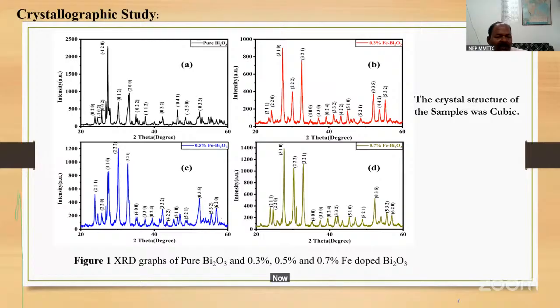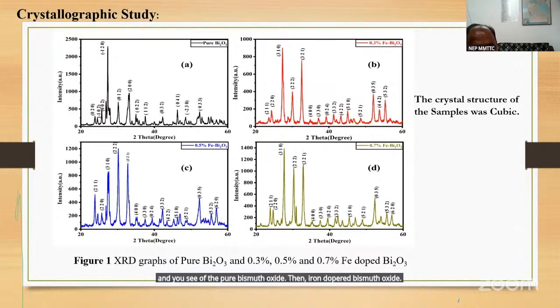Now these are the X-ray patterns, and you see the pure bismuth oxide, then iron doped bismuth oxide 0.5%, 0.3%, and 0.7%. And these are the crystal structure of the samples. And this means A is equal to B is equal to C. That is the cubic.